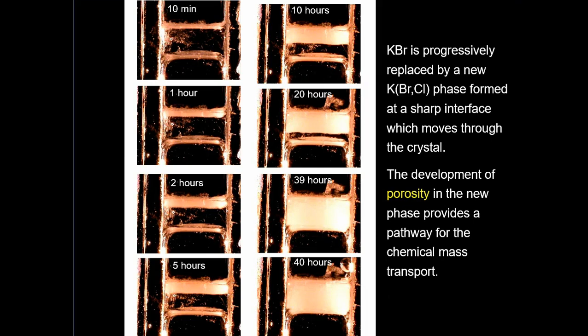We have, again, the same as the first experiment, a new composition, and it's a KCl composition. I've stopped it just in case it didn't work. So you can see where I've stopped the film, and you can see the progression. It took about 2 hours to reach the KCl composition. Oh, the first one was 2 hours. This is 40 hours of filming.